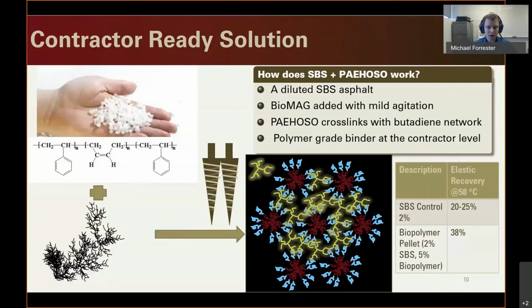And so we got the idea of what if we combine the SBS and the Biomag system ahead of time and get some of the reactivity between the SBS and the Biomag done before it ever touches the asphalt. You don't want to go too far, because then you start forming thermosetting materials that won't get dispersed, but can we get it started and speed up the process? And so we've done a lot of development with the Haake system on getting these biopolymers incorporated in SBS. And what we found was that we can do some pretty incredible things by doing some of that pre-reactivity, pre-blending.